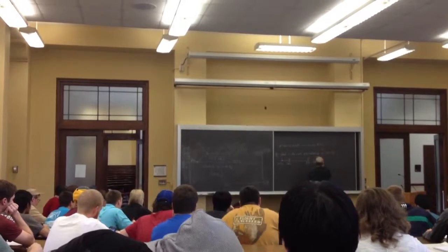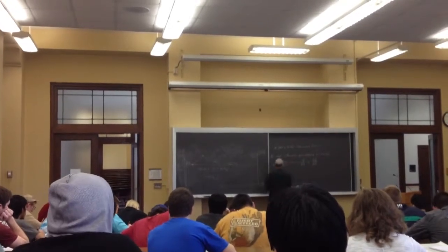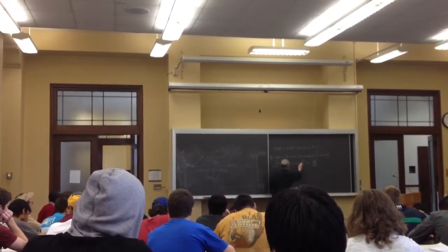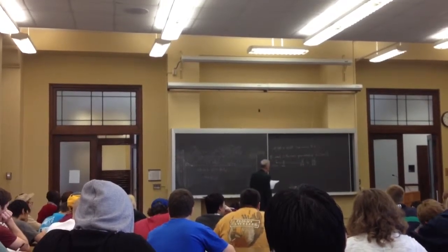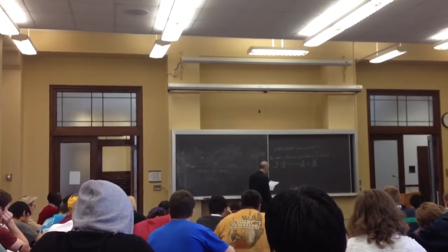So the percent alpha is going to be just like BB prime over AB prime. The whole thing is AB prime, and the opposite part of the lever is BB prime, which indicates how much ferrite's coming out.